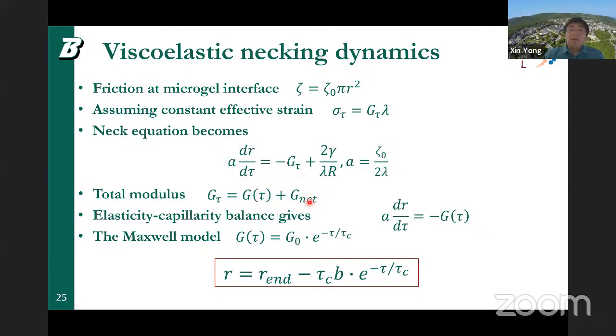So we argue that the total elastic modulus is contributed by a viscoelastic contribution of the polymer chain in the neck region, and then an elastic contribution from the deformation of the total network of the microgel. In the steady state, the total network contribution and the surface tension cancel each other. Therefore, we can also assume a quasi-steady state where they will cancel each other at all times. So the neck change will be governed essentially by the viscoelastic contribution. Using a Maxwell model, we can obtain a very simple exponential relation, where the only two fitting parameters are this B and the characteristic relaxation time of the chain.